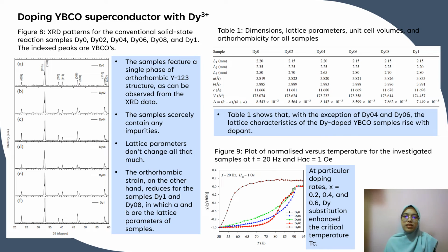The orthorhombicity, on the other hand, reduces for the samples Dy1 and Dy08, in which a and b are the lattice parameters of the samples. Table 1 shows the dimension, lattice parameters, unit cell volume, and orthorhombicity for all the samples. Table 1 shows that, with the exception of Dy04 and Dy06, the lattice characteristic of the Dy doped YBCO sample